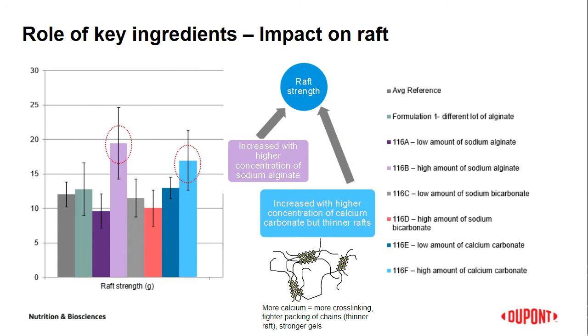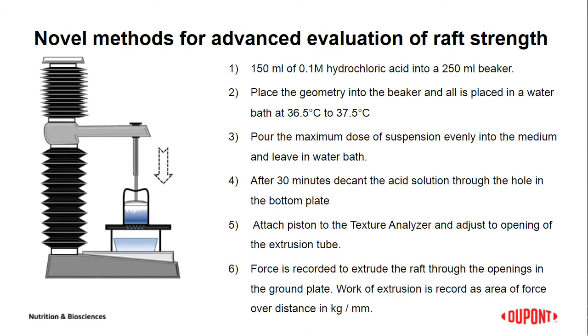We will discuss the role of key ingredients and their impact on the raft strength. A study was carried out to understand the key ingredients in the raft formation by varying the amount of sodium alginate, sodium bicarbonate, and calcium carbonate in the suspension formulations. The study revealed that the raft strength increases with increase in the concentration of the sodium alginate as well as the calcium carbonate by forming stronger gels. The results are represented in the bar graphs on the left side of the chart. I'm handing over to Matthias for the continuation.